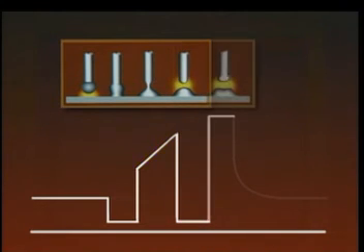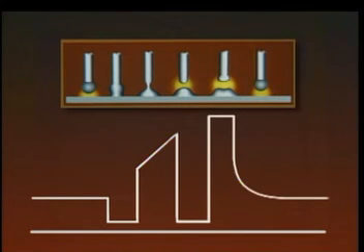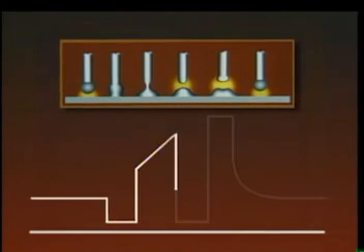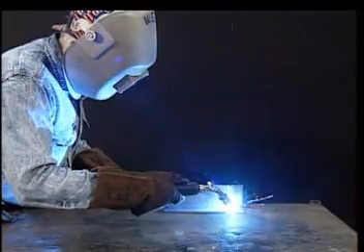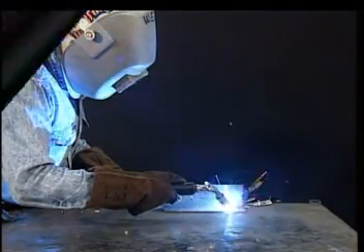It melts the electrode back. This reduces spatter and fume generation. The arc current is then reduced to the background level in a controlled manner, reducing weld puddle agitation. It is the instantaneous control over the current that eliminates the highly violent and explosive energy of short arc MIG welding. Now, what if we applied waveform control logic to more than just short arc MIG?